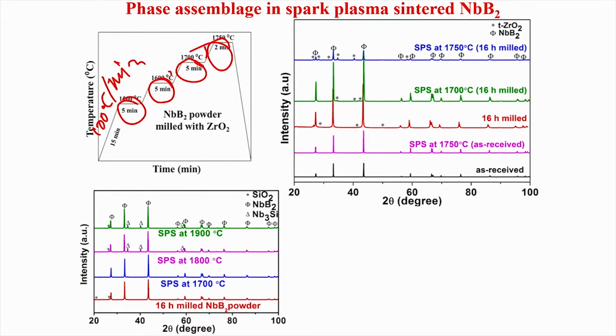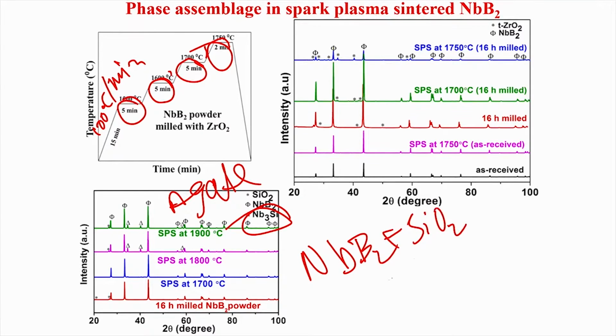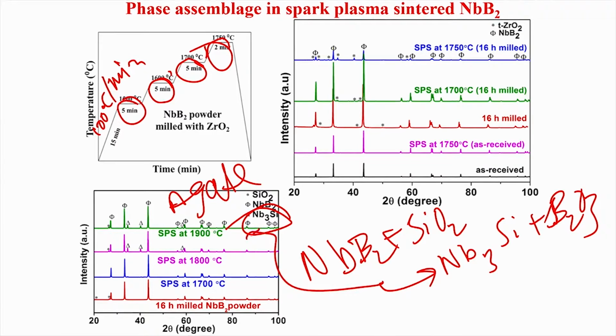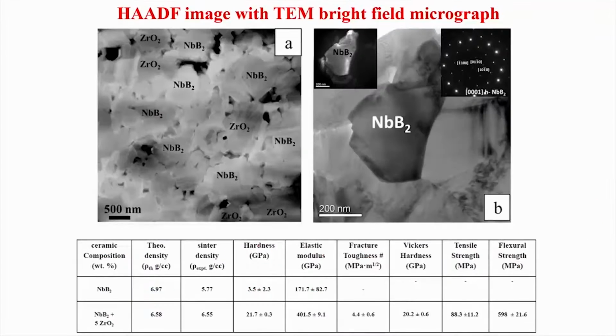And what you notice here, when it is spark plasma sintered at 1750 degrees Celsius, this niobium boride with zirconia milled powder, you can see there is a clear presence of the tetragonal zirconia. But when you use agate as a ball mill, then there is a second phase, apart from silica, a third phase called Nb3Si. So the niobium boride reacts with silica and forms this Nb3Si, and also forms boron oxide. Okay. So this reaction essentially takes place during the spark plasma sintering of these materials.